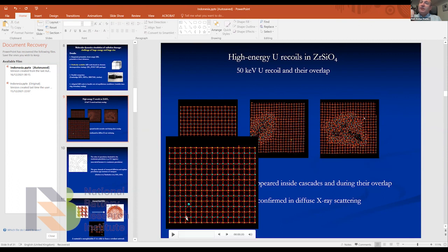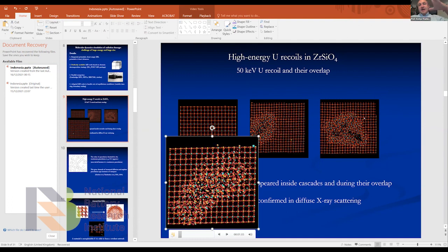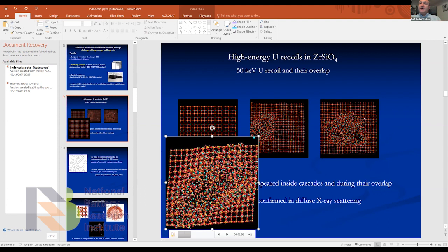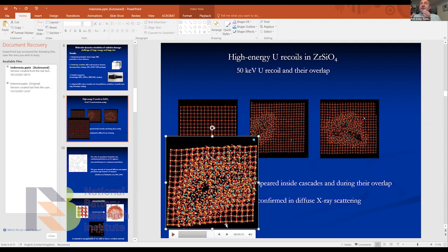What seems to be happening is that when this guy moves around, it creates depleted regions in its path and densified regions in the core. When all this gets overlapped, we can expect density variations, right? So we can have slightly decreased density and slightly increased density. And these are not large effects, right? We're talking maybe about 10–20% changes of density here in the core.